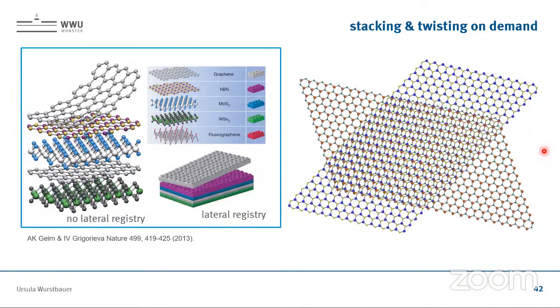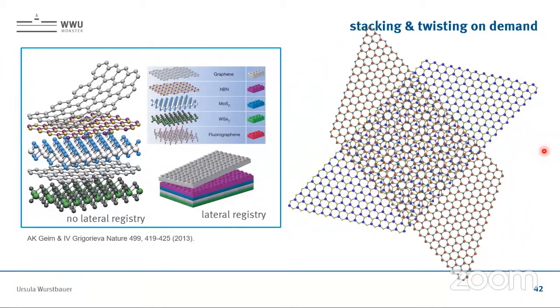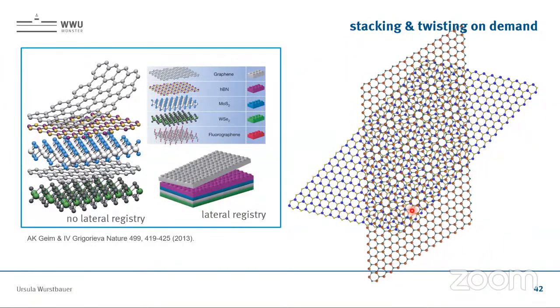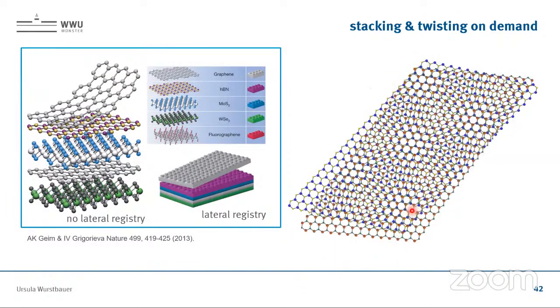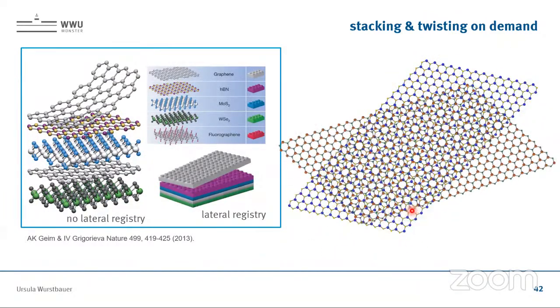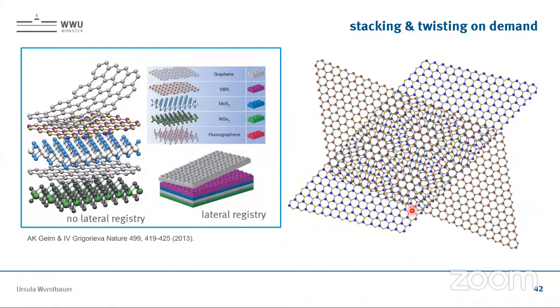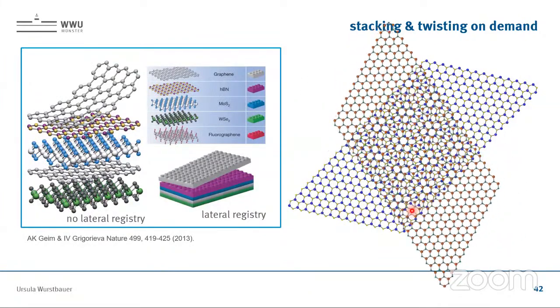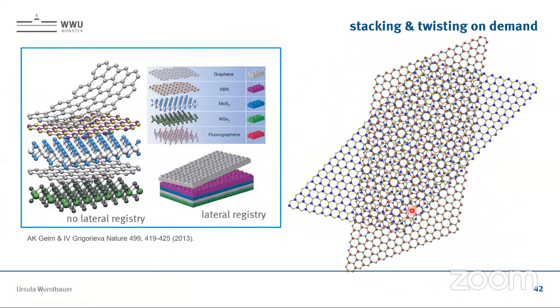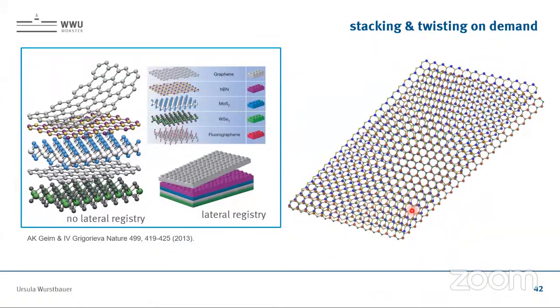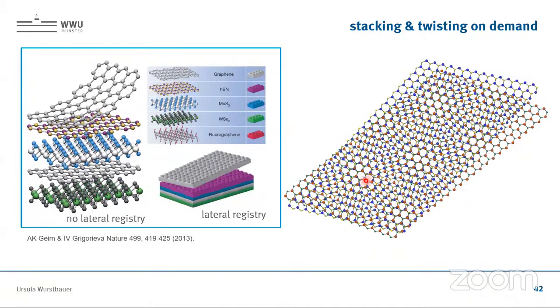And now if you look at this, during this rotation, you see a different pattern forms depending on the rotation angle, and of course also a little bit on the lattice constant. But if we have the same lattice symmetry, which is given by the 2D materials, hexagonal for most of them or a lot of them, we get a hexagonally superimposed pattern. It's called a moiré pattern, maybe also known from digital photography. And this moiré pattern can generate a lot of effects.